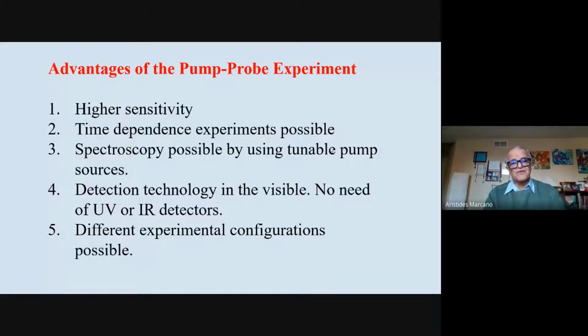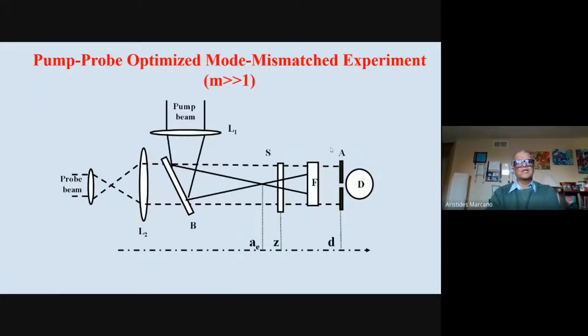And of course, you can have a variety of different configurations possible with this experiment. But this is the configuration we call the optimized one, because we demonstrated that when you use a continuous wave light, this is one possibility for having the maximal signal you can get. Here, for example, you have your pump beam being focused and the probe beam being collimated. That's the configuration I recommend for doing the experiment if you are using continuous wave pumping. And then you just block your pump beam again, and you observe the changes over the probe beam using the aperture and the detector. That configuration provides you an optimized version of that.